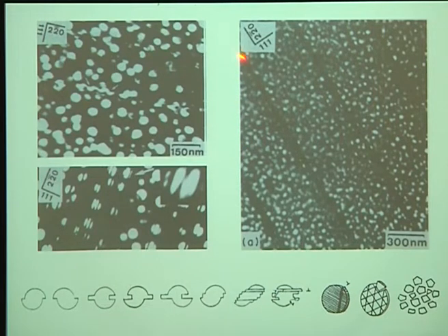And in fact, similar to that, if you see where the number of cycles is large, you see regions where precipitates could not be seen, correct? This region could mean that it is below the resolvable size, but the particles are there. That's one possibility, or the precipitate itself has dissolved. These are the two possibilities which occur in this case.